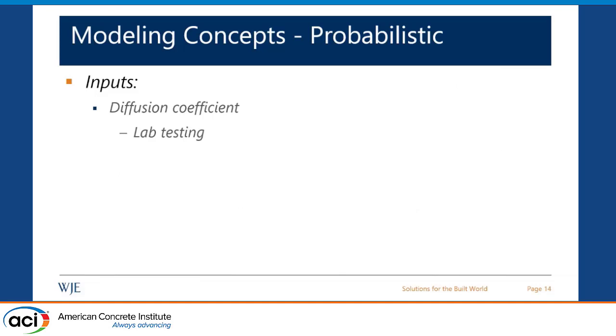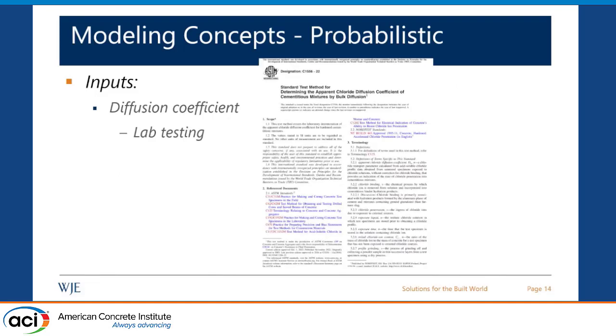For the diffusion coefficient, we like to rely on lab testing. This can be C1556, where you test saturated samples and expose them to sodium chloride solution for a specific exposure period. In the standard, it's defined as at least 35 days. And then you look at the chloride profile, and based on that, you estimate your diffusion coefficient.